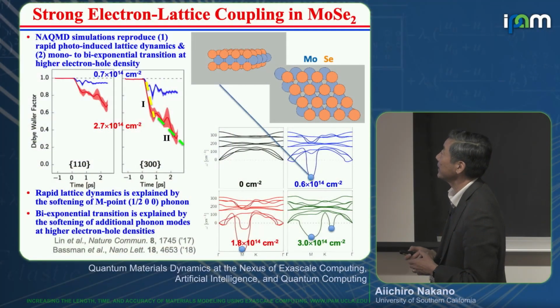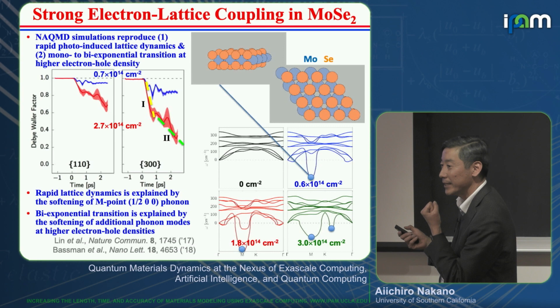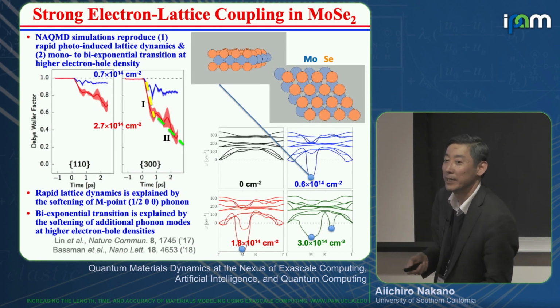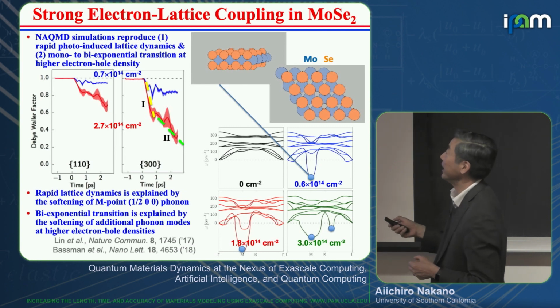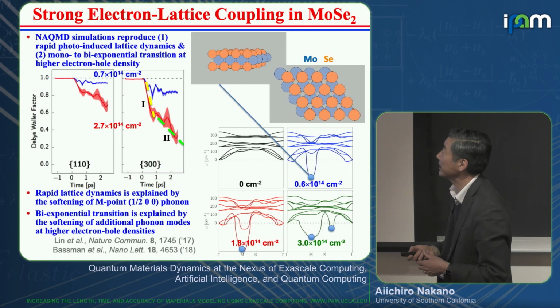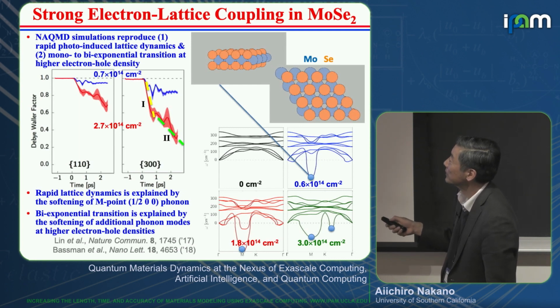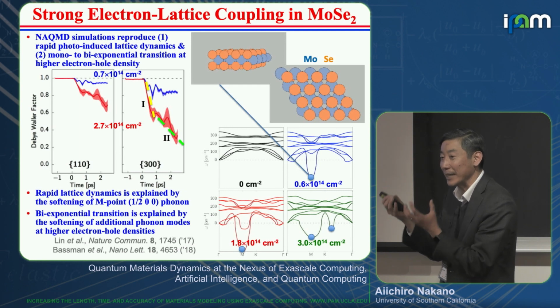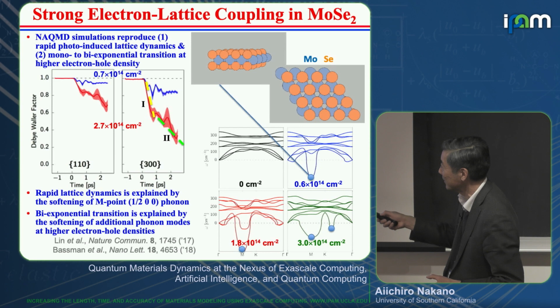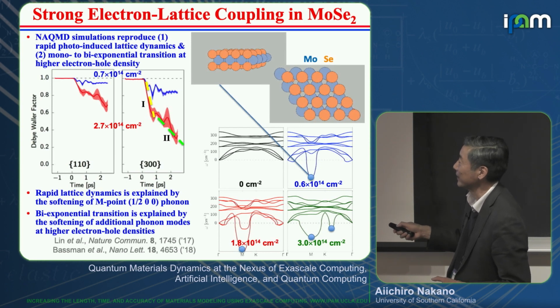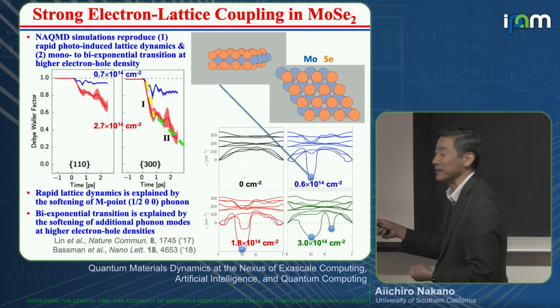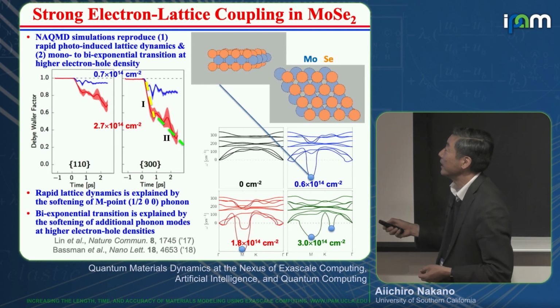So this is one of the examples. It's an extremely strong laser, and we found that the strong laser light is transformed to lattice motion with almost 99% quantum efficiency in molybdenum diselenide monolayer. So NAQMD simulation reproduced the rapid photo-induced lattice dynamics. This is the so-called Debye-Waller factor, a kind of disorder of the lattice. One is the perfect lattice, and the deviation from one is the disorder. Within a picosecond, the photon energy is converted to lattice energy. We computed the quantum efficiency and it is very high. And then also we reproduced the so-called mono-exponential, one time scale, to bi-exponential, two time scale